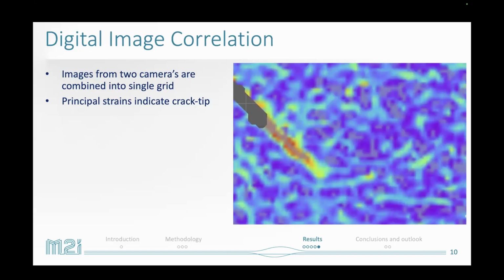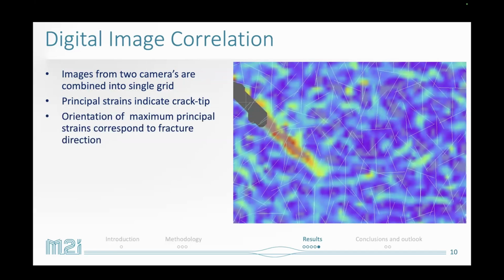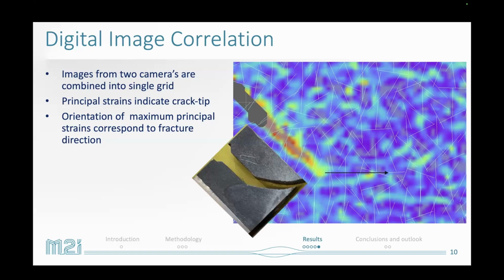So if we zoom in a bit, we have this area in which there was no correlation on the top left. That was the initial notch made, and then we have this area with a high maximum principal strain, and this is the pre-crack length. And if we qualitatively look at the orientation of the maximum principal strains, which is a bit hard, that is indicated with these lines. And as also indicated in one of the earlier presentations, there are a lot of knobs which you can turn in this DIC evaluation, depending on your facet size, depending on your resolution. But qualitatively speaking, this is more or less the direction perpendicular to your maximum principal strain. And that corresponded for this test to the final crack path. But this is something I'm looking into more.